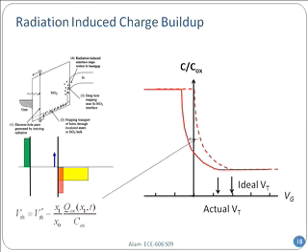And what happens is that the electrons, because of the electric field, very quickly leave. But the holes are not as fast. They are heavier, so it takes a certain time, and then they can get trapped and become like an interface trap. So this is that QF, the fixed charge at the interface.